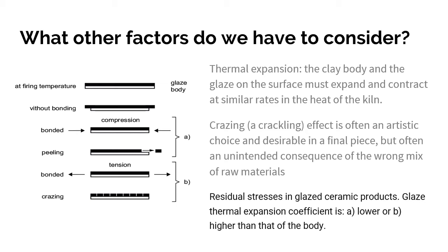In the heat of the kiln, every piece is going to expand and contract. So the clay and the glaze need to expand and contract at similar temperatures and bond together. If the clay is shrinking too quickly, the glaze is going to peel off. If the glaze shrinks too quickly as it cools, you'll get crazing, and crazing is that crackling effect. Often it's an artistic choice, but it's often an unintended consequence of the wrong mix of raw materials. So here's a little image of the peeling versus the crazing, and really we're trying to get the glaze bonded to the clay body to make a stable piece that will last for years. And also if you're trying to make it food safe, if you want it to be a serving bowl, something that has a lot of crazing or crackling or peeling could lead to glass chips, which would be undesirable in a piece that serves food.